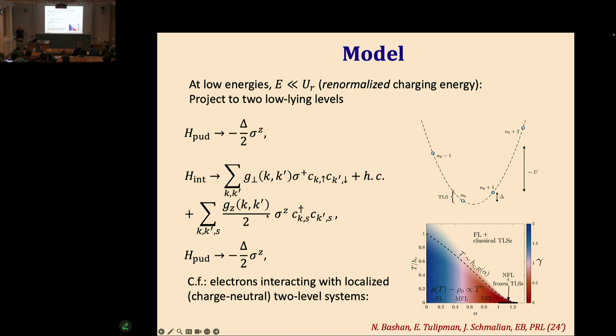It turns out that these low energy excitations indeed can give you deviation from Fermi liquid. The scattering rate in particular is not linear in T. It turns out that in this problem, you can get a resistivity exponent as a function of temperature which is a continuous function of the microscopic parameters of the problem. It turns out that there's something very special about linear in T resistivity when it comes to superconducting puddles in particular. That was the interesting thing we found here.